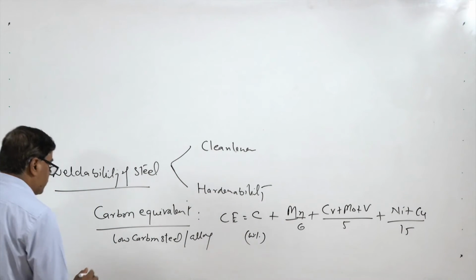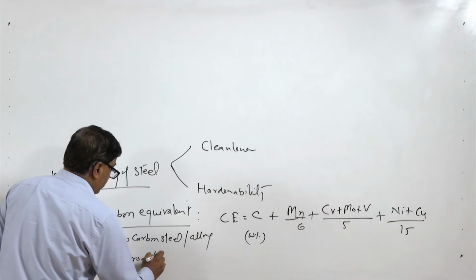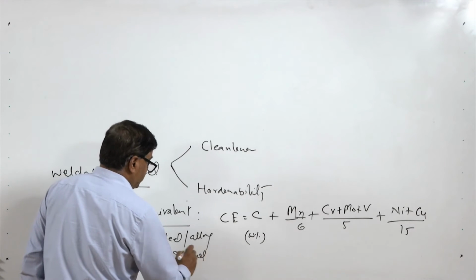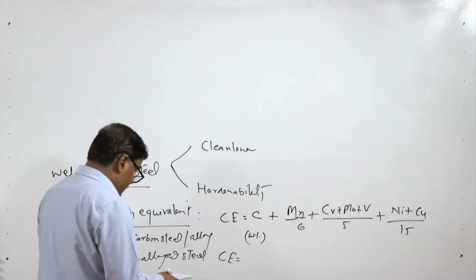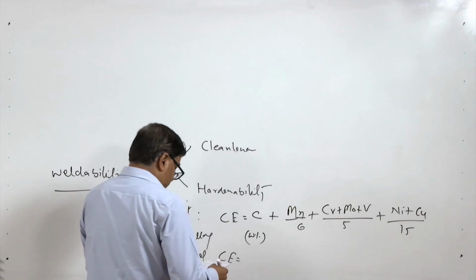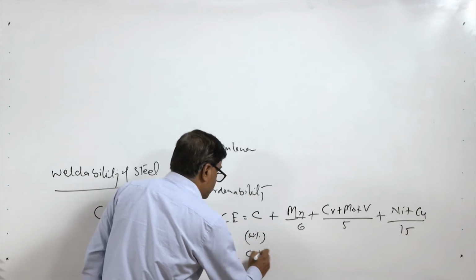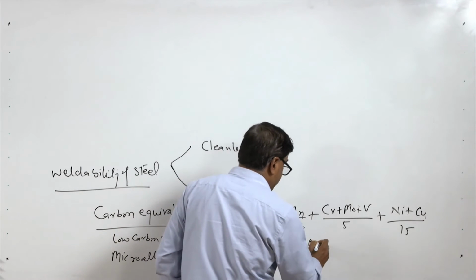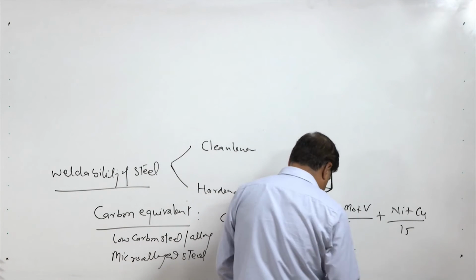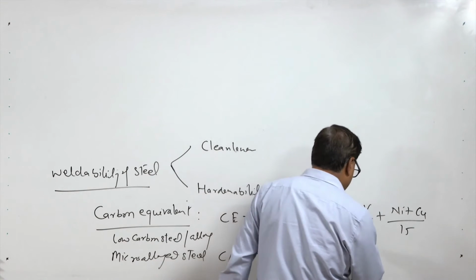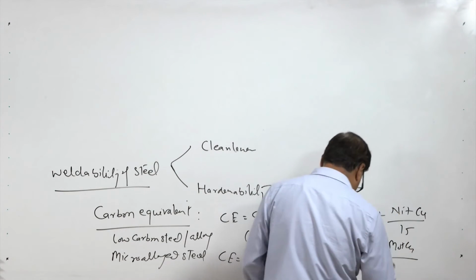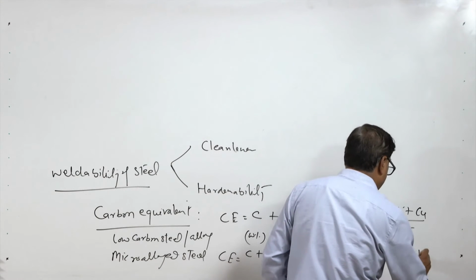Another equation, which is used for microalloyed steel to determine the carbon equivalent, goes like this, where CE is equal to C plus silicon divided by 25, plus manganese, chromium divided by 16, plus nickel, molybdenum, copper divided by 20, and then vanadium divided by 15.